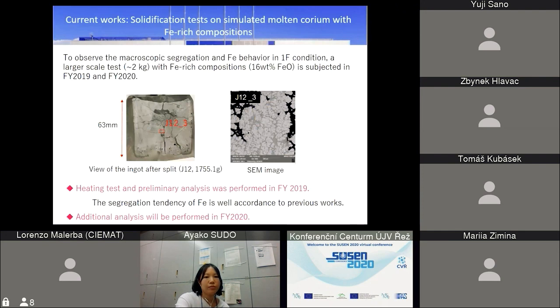This is a view of the solidified ingot after splitting, and a SEM image. Complex phase separation occurs with iron-rich composition, but the segregation tendency of iron is in good accordance with previous work. Currently, additional analysis will be performed this year.